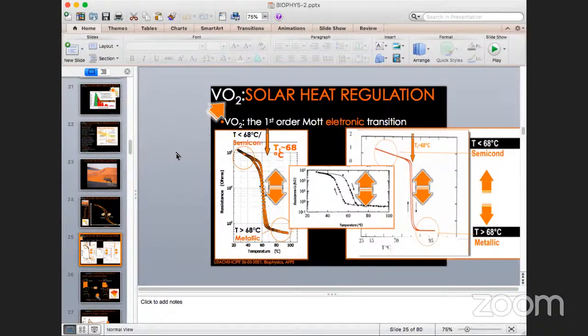Correct, Michel, you are absolutely correct. In effect, before, the challenge was to reduce, to shift, to tune that temperature. And indeed, it's possible to tune it by doping with tungsten or molybdenum.